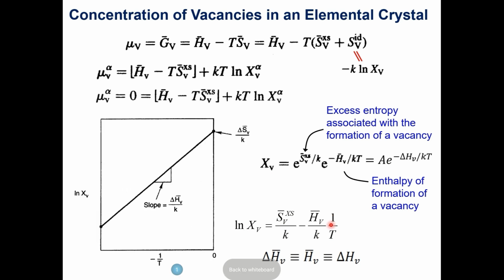That should look something like this. And from the slope of the line, you actually calculate this enthalpy for creation of vacancies—very, very important for us. This is what people do in the experiment: they will actually take a sample, take it to different temperatures, and get a straight line fit. You need at least two data points to draw the line, because anybody can draw a straight line through one point.